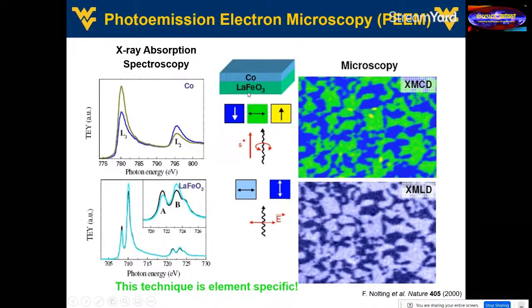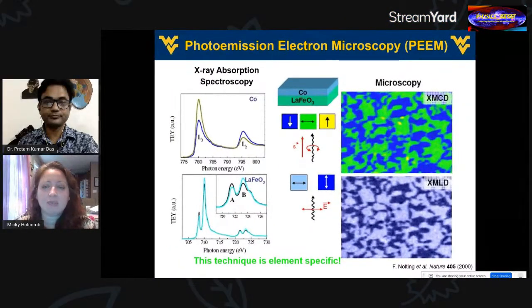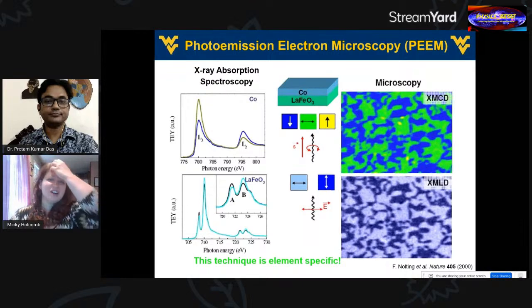So if you look at the iron edge, now you can look at the magnetic domains in this antiferromagnet that is under the cobalt, and you'll see if you image these that they actually share the same domain structure. So these are two systems where they have magnetic domains and they are coupling across the system.